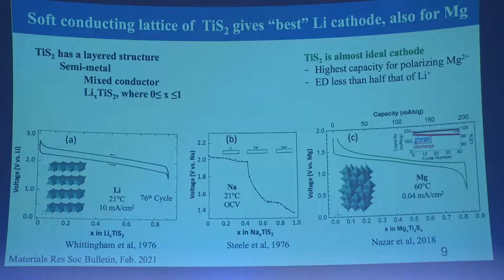So maybe 10 years ago, there's a lot of push. Magnesium's going to be the answer. We can get 2 electrons in. But it wasn't until Anton van der Ven at Santa Barbara did theoretical calculations of the voltage and said the voltage is going to be about a volt lower, that people started looking at it. And the Canadian work was after he did the calculations, and it was within 50 millivolts of what he had calculated. So you can see that commercially there's very little interest in magnesium anymore.